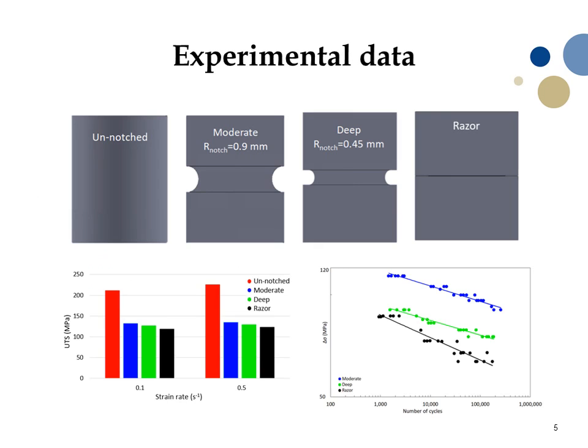To this aim, tensile and fatigue data available in the literature has been considered. Unnotched and differently-notched PEEK samples — circumferentially cracked and U-notched specimens with different notch radii — have been tested by other authors in a phosphate buffer saline solution at 37 degrees Celsius, and they have been here analyzed in terms of the strain energy density approach.